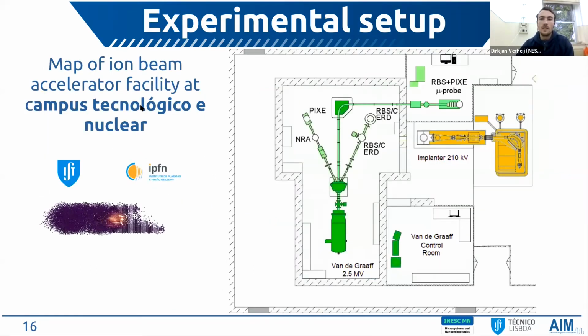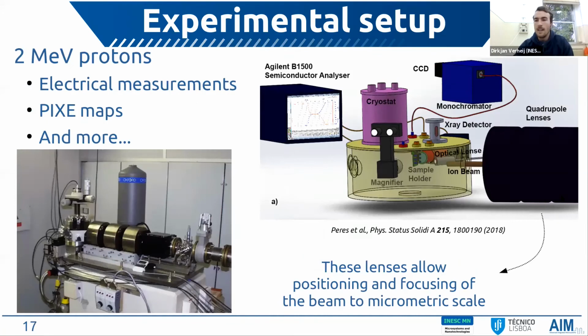So now moving on to the actual important part of our work, which is the irradiation of the samples, which we do at the Campus Tecnológico Nuclear at the Ion Beam Accelerator facility, of which I show a map here. And we use for our experiments the Van de Graaff accelerator, which can accelerate protons up to an energy of 2 mega electron volts. And these protons are then directed through this line here to the microprobe chamber. This microprobe chamber has the interesting feature that it can focus and position the beam to a micrometric scale. So the beam spot size we use during these irradiations is of a size of 2 by 3 micrometers.